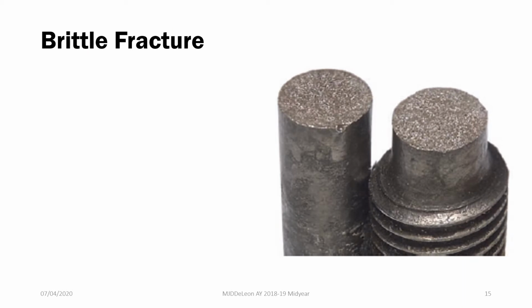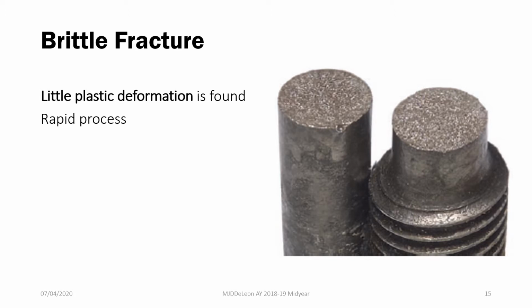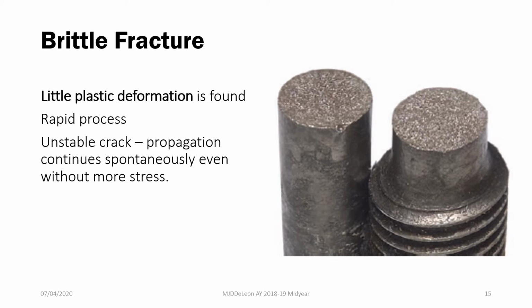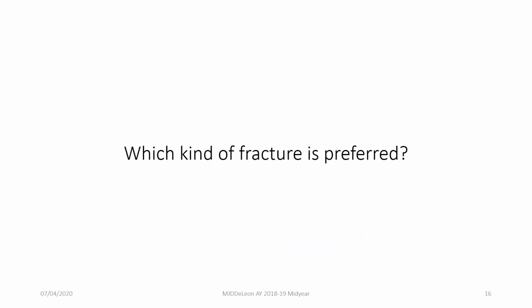Next, for the brittle fracture, we can see that there is little plastic deformation found. It's a very rapid process. Para nag-snap lang siya into 2, wala ng plastic deformation nakita. And the crack propagation is termed to be unstable. It would move spontaneously even without additional stress applied to your material. So this results in a flat fracture surface. So pag nakita mo perfectly flat yung fracture mo, this is a characteristic of a brittle fracture.